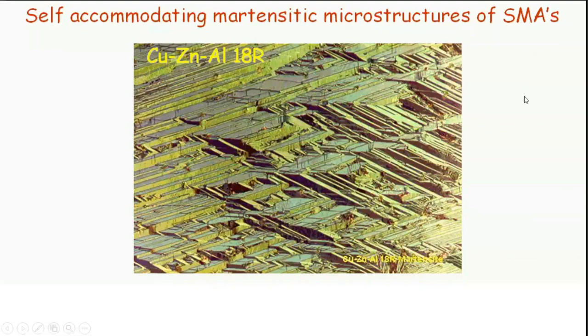So the thing to take away from this, one thing I need to mention before that, there's an optical microscopy and an optical micrograph, and the contrast has been given by using polarizing filters. So that's the way you're able to see these different variants, because this is a monoclinic martensite, so it's active under polarized light, and you're able to see these variants.